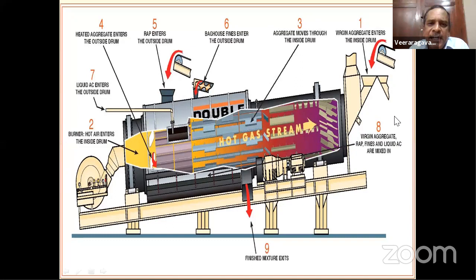So this is a double barrel drum from Astec, wherein there are two drums, one inner and one outer shell. I allow the aggregates to get into the inner drum. I input the flame here, a hot gas stream. It heats the aggregates. These hot aggregates in turn will be shifted to the outer drum shell. In the outer drum, they are not directly exposed to the flame. With this, we will be able to use a higher percentage of RAP, but studies are to be carried out.